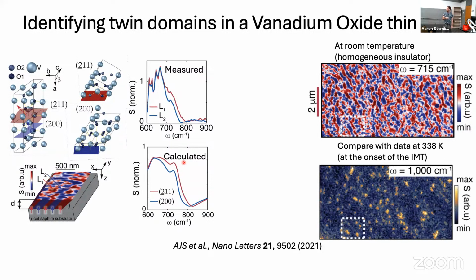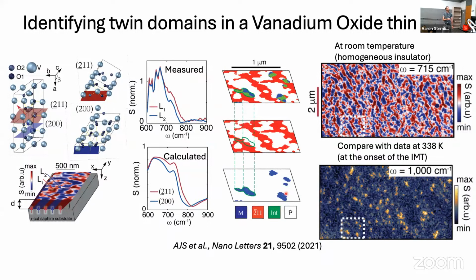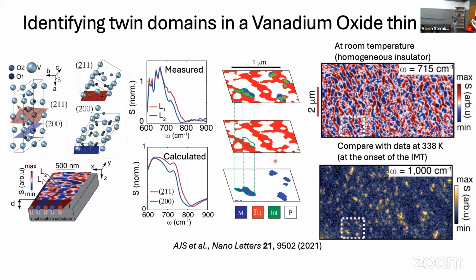Now we can compare that twin domain structure with the conductivity, which is all we have to do is basically increase the infrared frequency to a higher energy where lattice vibrations don't impact the measurement, and heat up the film a little bit to the point where metallic nuclei first appear in this film. And then we can see increase of contrast, which is indicating the locations of domains in the film, which is inhomogeneous. And we compare that to the location of twin domain boundaries in the same film. And we saw a pretty strong correlation suggesting that these metallic nuclei tend to show up at twin domain interfaces.